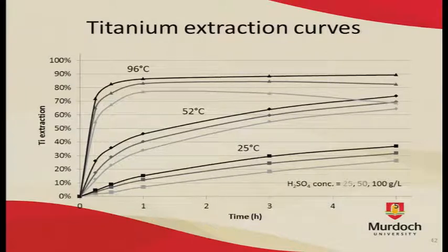in solution. Now, this effect is most apparent in the high temperature weak acid leach curve up there, in that titanium was frequently observed precipitating out after dissolving. So that was the secondary titanium dioxide product I was talking about earlier. The solubility of titanium will decrease with increasing temperature, and of course it's more soluble in concentrated acid. So unsurprisingly, it was in hot dilute acid that the greatest amount of titanium precipitation was observed, as it's most soluble in cold concentrated acid.